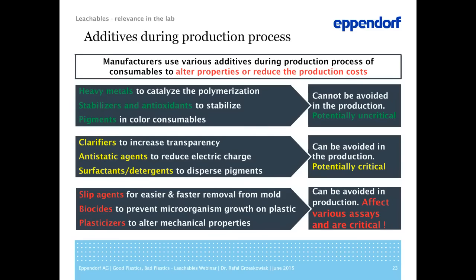These substances cannot be avoided during the production process. They have to be added simply to make the polymerization possible and make sure that consumables remain stable for a reasonable period of time. So they are regarded as potentially uncritical, and there is not much evidence in the literature of their effects on experiments. However, I would state clearly here that depending on the experimental conditions and also assay methods used, particularly sensitive analytical methods, they also may have certain influence on experiments. So despite they look green here, they still might be an issue.